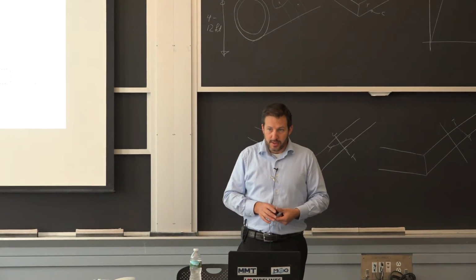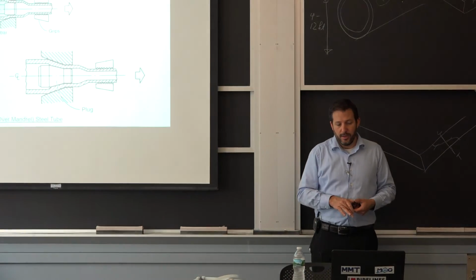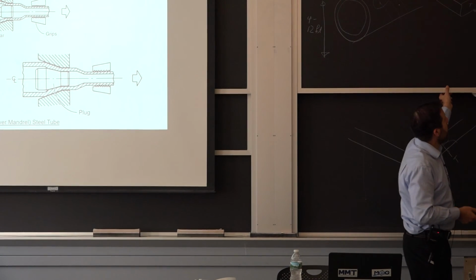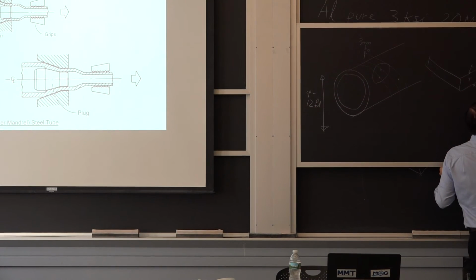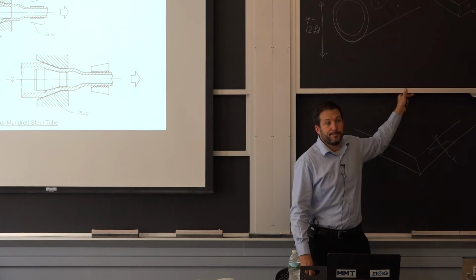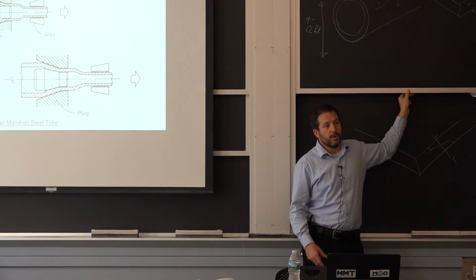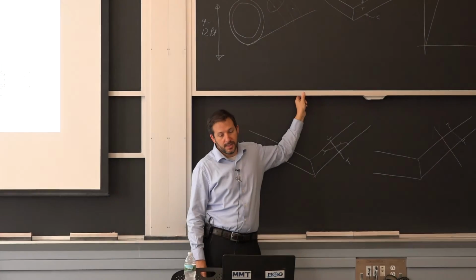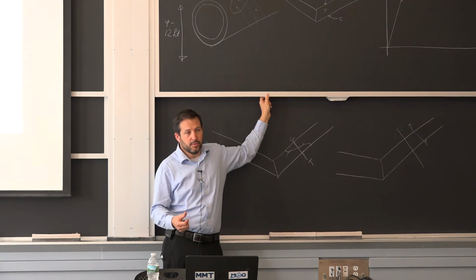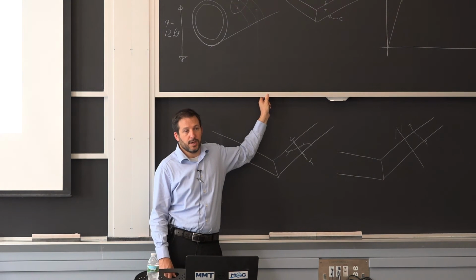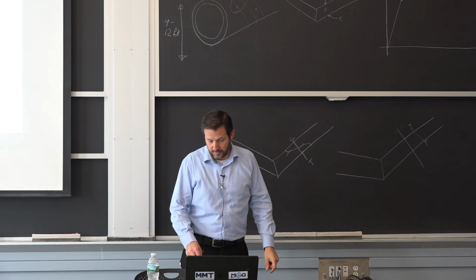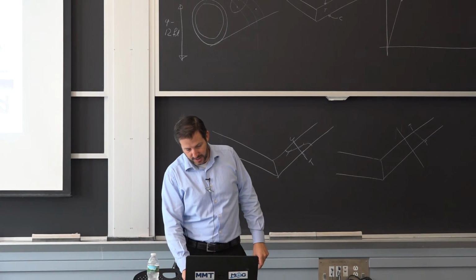if that's something you're interested in. So to be able to do drawing, you need the material to have this hardening. So you don't want to do it at super high temperature. You do it cold enough that it creates the hardening when it's deforming, and so that helps you with your dimensional control. So a lot of times if you want a pipe that has very tight dimensions, it's going to have to be drawn as the last step.